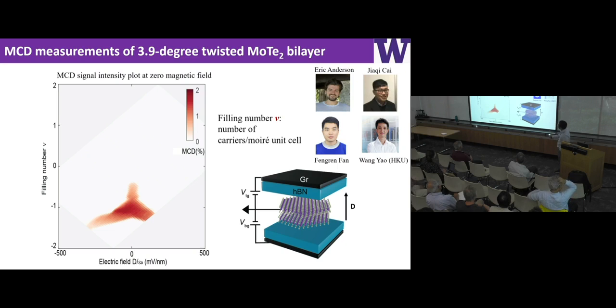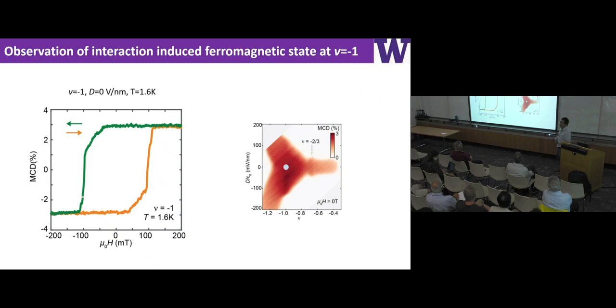In this diagram, the vertical axis is the filling number, meaning the number of carriers per Moiré unit cell, and the horizontal axis is electric field. And you can see that in this large phase space, only at the hole doping side do we have this non-vanishing MCD signal, which suggests we have a ferromagnetic state. And there are also two features here corresponding to the fractional filling and also integer fillings. Just to confirm, we do have these ferromagnetic states.